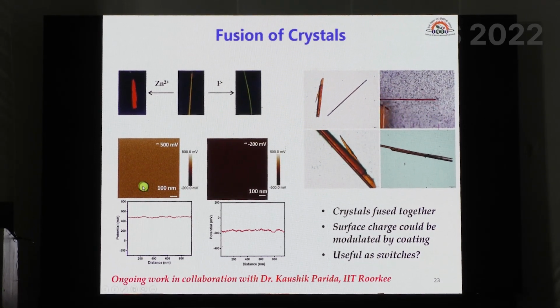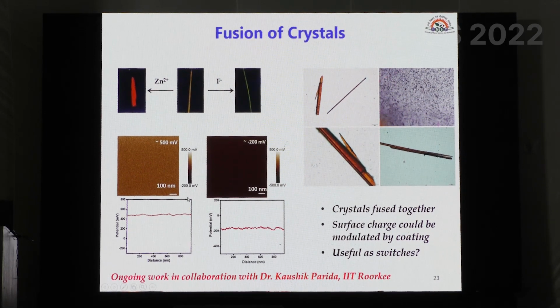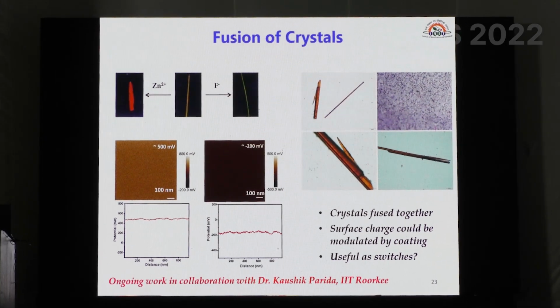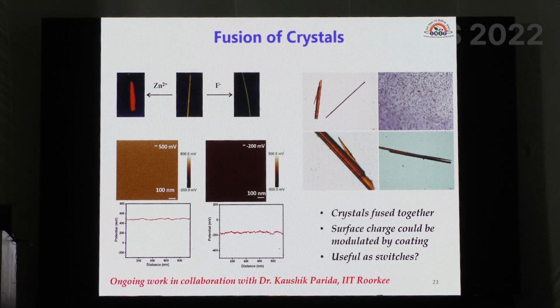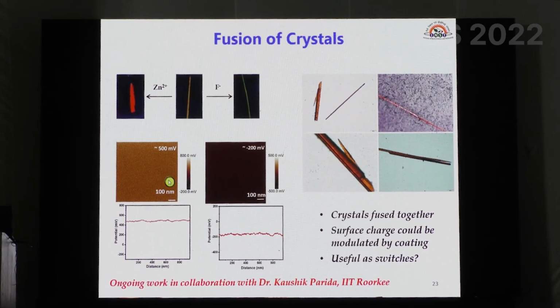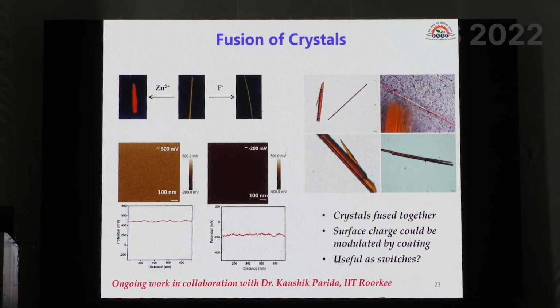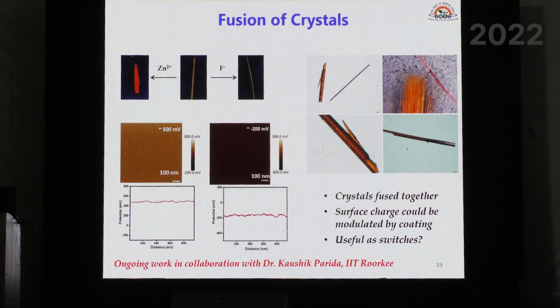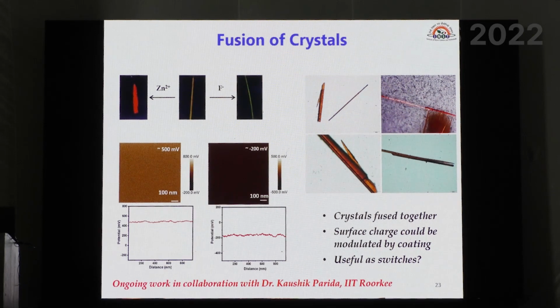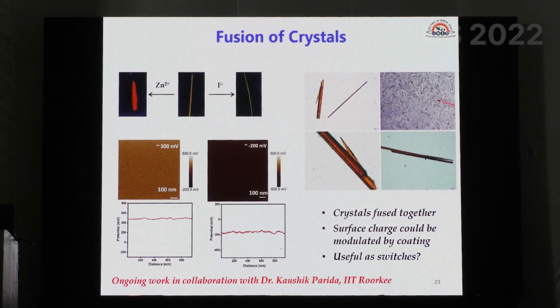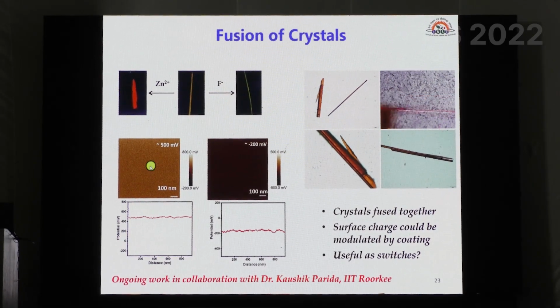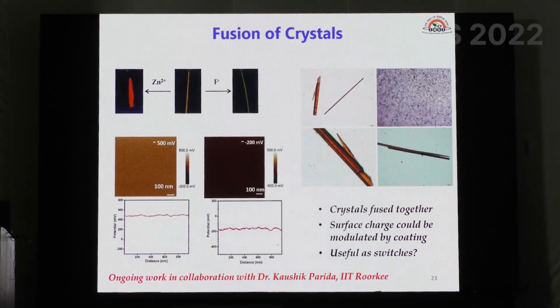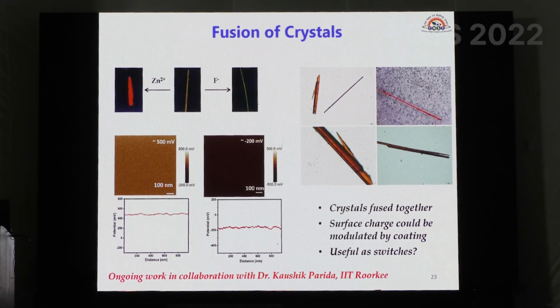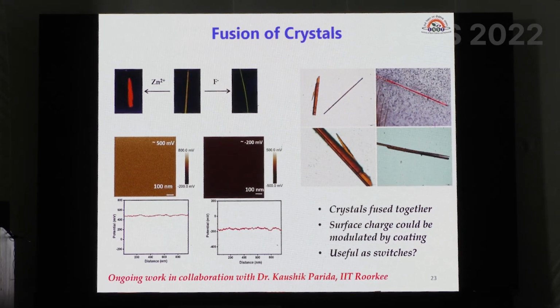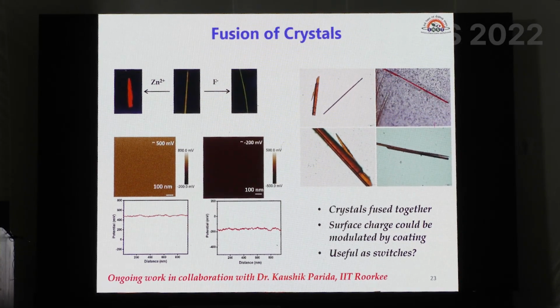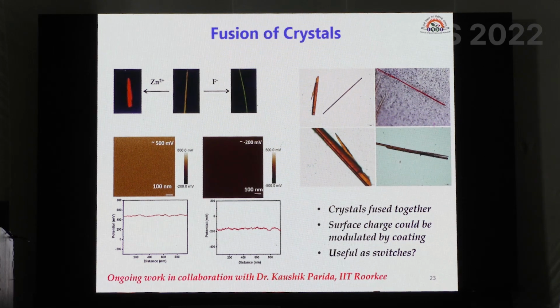So these are Kelvin probe force microscopy images that measure the surface charge on these crystals. When we measure these, we can see that the pristine crystals, what we start with, are close to zero or a little on the positive side. But when we coated it with zinc, the charge increased to almost 500 millivolts. But when it is coated with fluoride, the charge becomes about minus 200 millivolts. So the same material, depending on the treatment, is giving different charges.